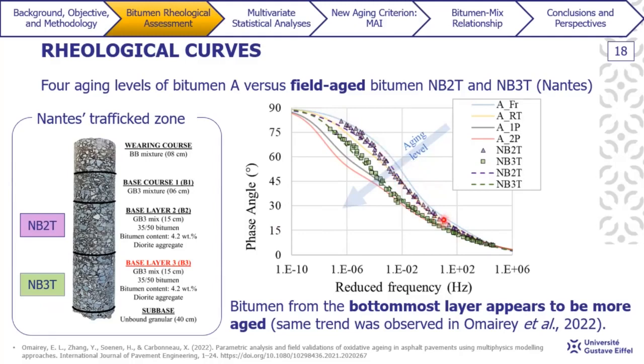When we see the trend that was observed so far, we observe that the bitumen extracted from the intermediate part seems to overlap the RTFOT curve, sort of, whereas the bitumen extracted from the bottommost layer seems to be in a zone between RTFOT and 1 PAV aged. So in this case, bitumen from the bottommost layer appears to be more aged, even though the overwhelming majority of studies state that aging is only relevant near the pavement surface, which would be here. In this work, we observed that the bottommost layer seems to be more aged than the intermediate layer that is closer to the surface.